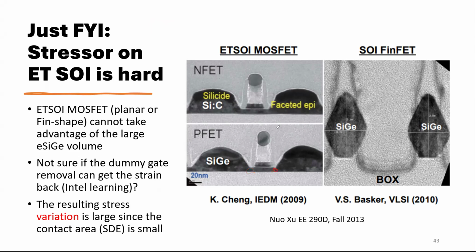So this is for their 22 nanometer. It worked. But when you want to scale, say 12, even lower, you have a problem. We talked about that last time for FDSOI, right? These are a bit thinner. Then you have a problem. And you want to grow thinner epi with a thinner SiGe layer. That's a big problem. Why is that a big problem?